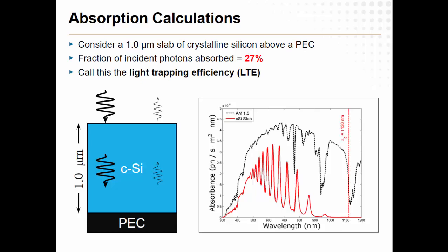Or sometimes you get terrible absorption because they constructively interfered. So that's a fun effect. It's called Fabry-Perot resonance, if anyone ever asks you that. But it just is what it is. So you integrate that, and you find that with a little structure like that, I am only absorbing 27% of all the photons I could be absorbing that are available to me from the sun.